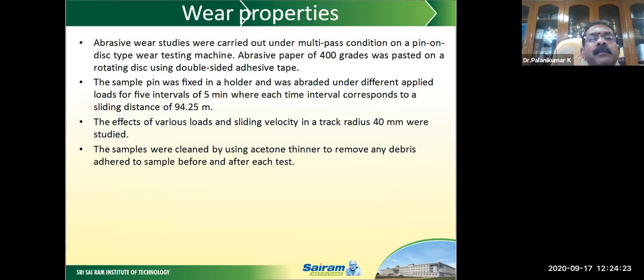Wear properties. Abrasive wear studies were carried out under multi-pass condition on a pin-on-disc type wear testing machine. The abrasive paper of 400 grit was pasted on a rotating disc using double-sided adhesive tape. The sample pin was fixed in a holder and was loaded under different applied loads for 5 intervals of 5 minutes, where each time interval corresponds to a sliding distance of 94.25 meter. The effect of various loads and the sliding velocity at a track radius of 40 mm were studied. The samples were cleaned using acetone thinner to remove any debris adhered to the sample before and after each test. So this is the wear test conducted on the pin-on-disc using the abrasive sheet.